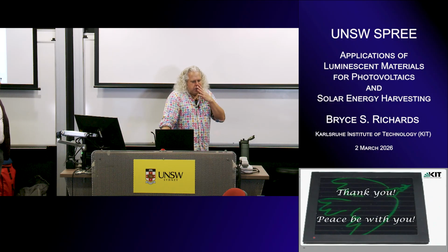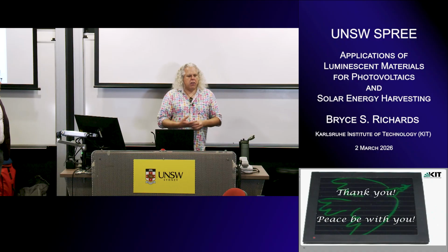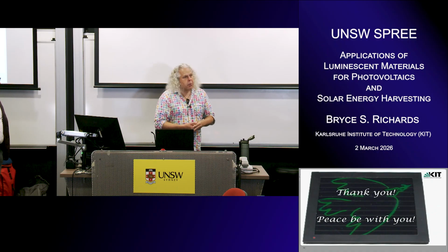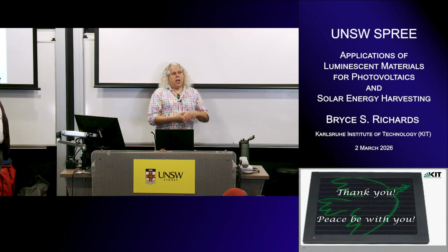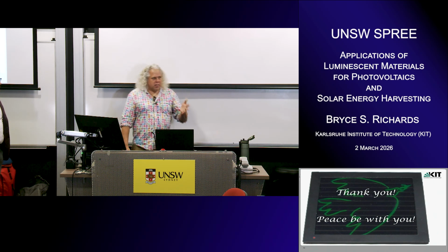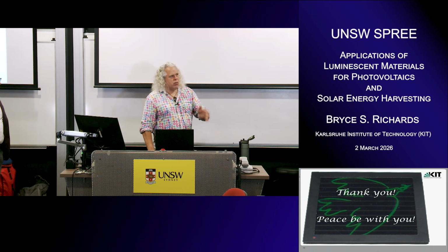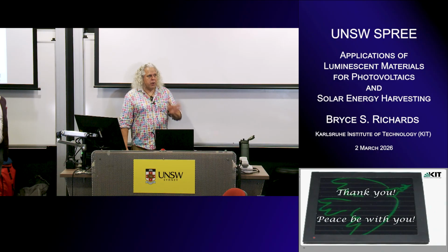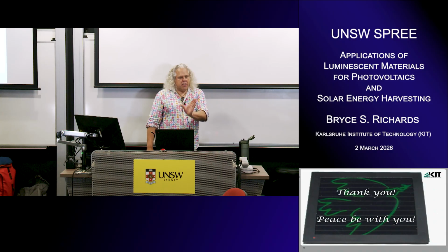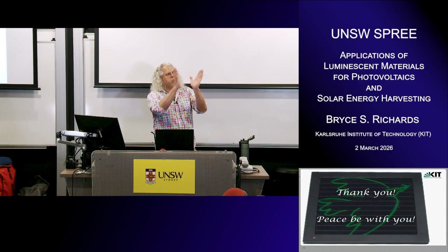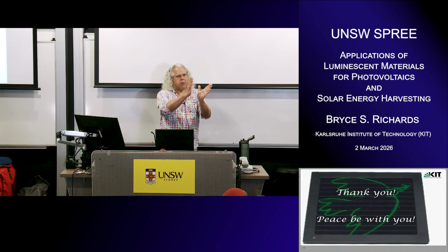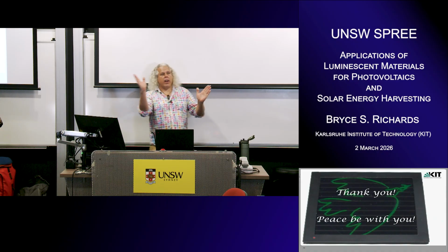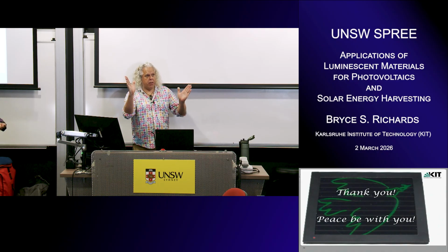To come back to the quantum yield question, normally we do calibration with a calibrated tungsten lamp, but you have to think that a tungsten lamp is not particularly strongly emitting in the UV. There's some, but you have to be really careful. Then you have to consider what you're trying to do: you're trying to absorb 300 to 400 nanometer photons, and with the same spectrometer, you're trying to look at the 1,000 nanometer photons.